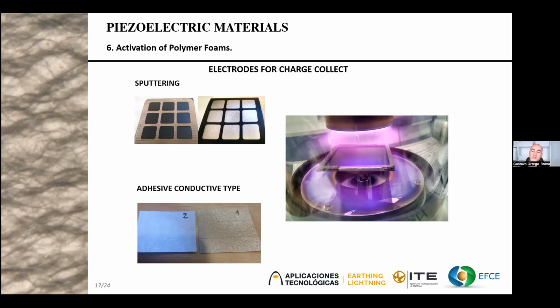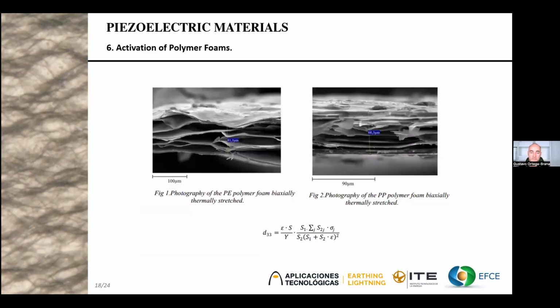To compensate for this problem, we use a shielding tape with a conductive rubber, as we can see in the figure below on the left. The only modification that we did for our material was a thermal biaxial stretching, because this process is beneficial to increase charge storage and reduce the Young modulus, and the result is an improvement of d33.